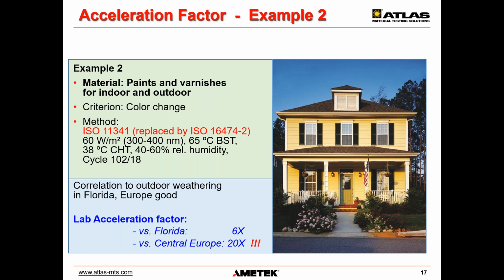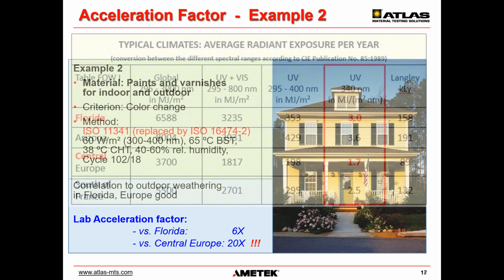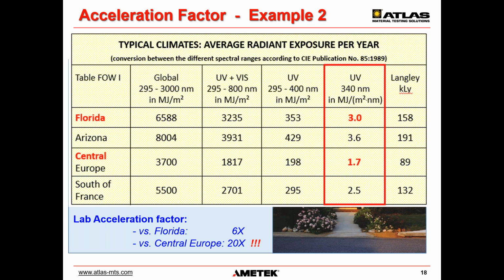Example number 2 is also on coatings. Note that the test method is quite similar to example number 1 with comparable irradiance, black standard temperature, and relative humidity set points. But note the acceleration factors to South Florida are 50% higher, 6 times compared to 4 times in the previous example. And the comparison to Central Europe was 20x, or about 25% slower than the previous example, but still much greater than the approximate doubling that we would expect if we only looked at radiant exposure in Florida and in Central Europe. About doubling.